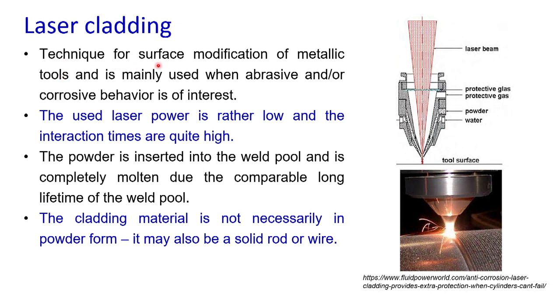So laser cladding is a technique for surface modification of metallic tools and is mainly used when abrasive or corrosive behavior is of interest. To improve the abrasive wear properties and the corrosive behavior of the work parts, we go for laser cladding. Laser power here is low. You notice that we are not applying higher levels of laser power, the power is low and the interaction time is quite high. So here we are maintaining the energy that we put in by way of more interaction time, although the power is less.